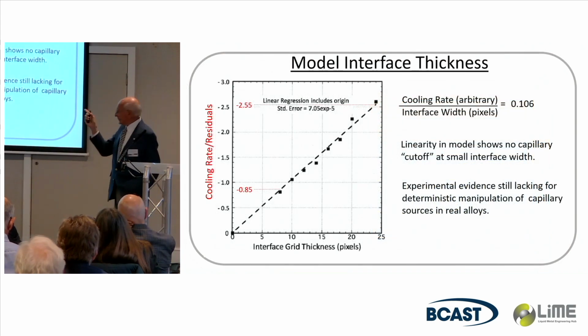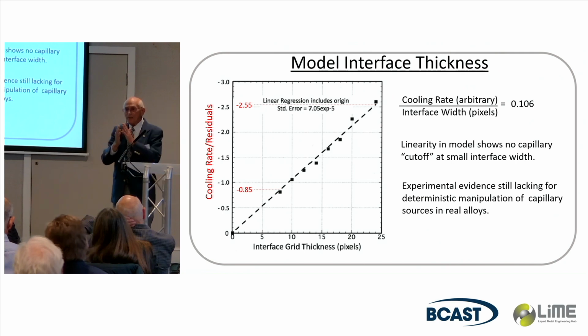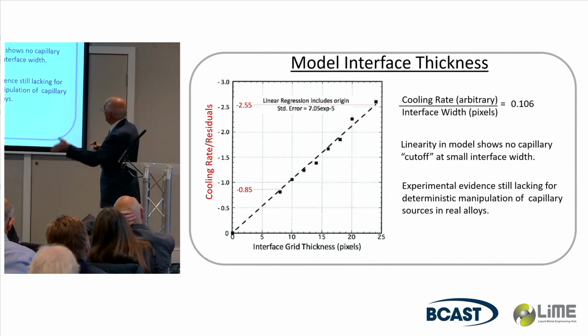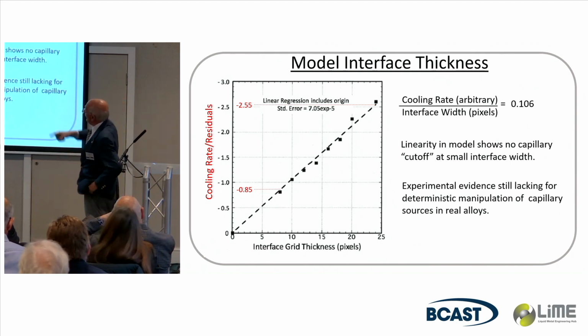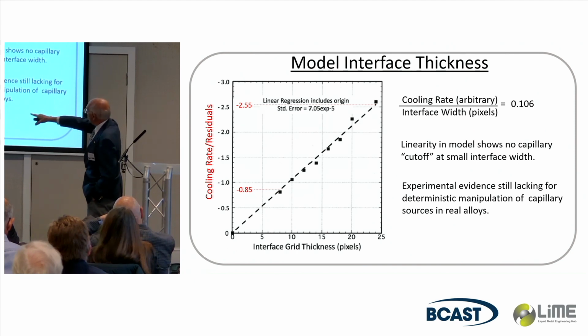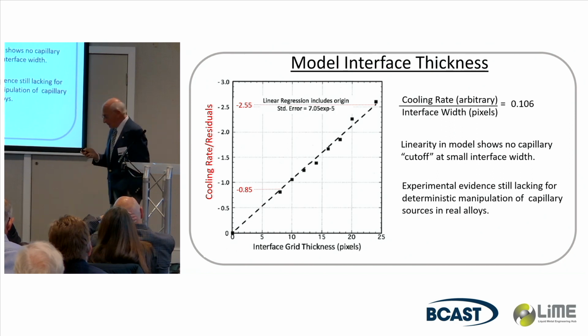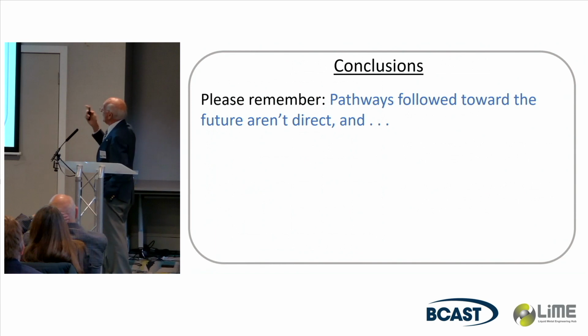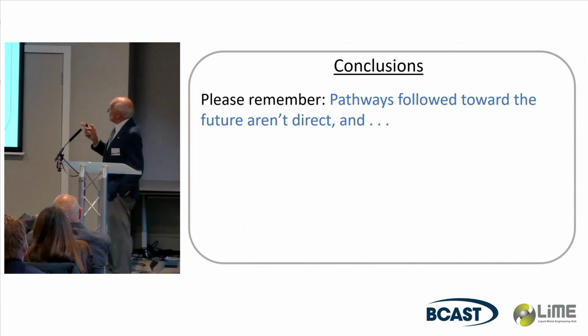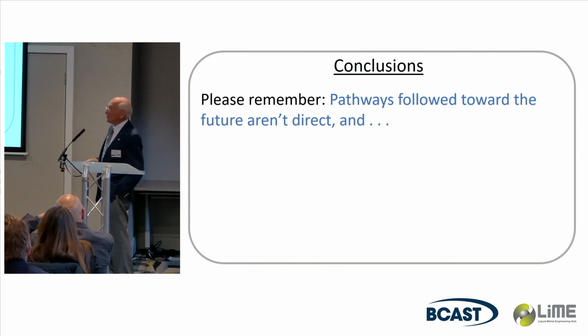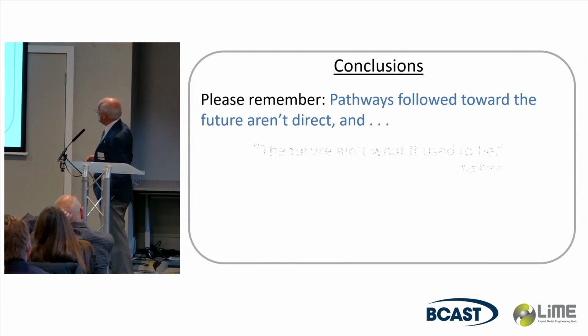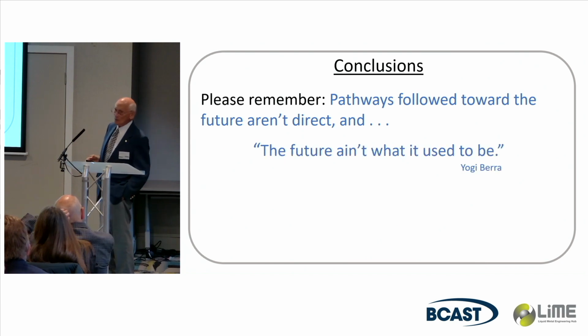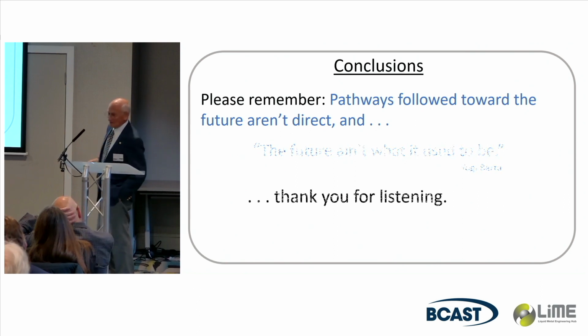To check, final slide, to see whether the thickness of the interface is allowing more or less of the currents to flow along it, we measured the cooling rate as these residual potentials as a function of the thickness of the interface, and indeed it's a linear result. So, here's my conclusion. Please remember the pathways followed toward the future aren't direct. And I'll use one more American quotation. The future ain't what it used to be. And thank you.